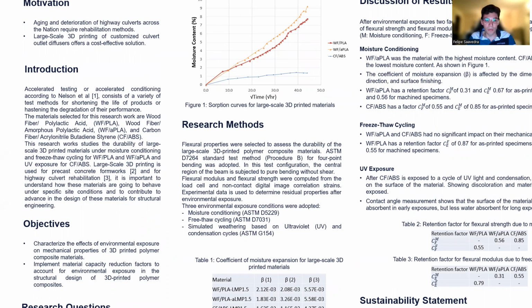The materials selected for my research work are wood fiber polylactic acid, known as WFPLA, wood fiber amorphous polylactic acid, known as WFAPLA, and carbon fiber ABS. This research work studies the durability of large-scale 3D printed materials under moisture conditioning and freeze-thaw cycling. This is for wood flour PLA and wood flour APLA, and for carbon fiber ABS, this material will be exposed to a cycle of UV exposure.